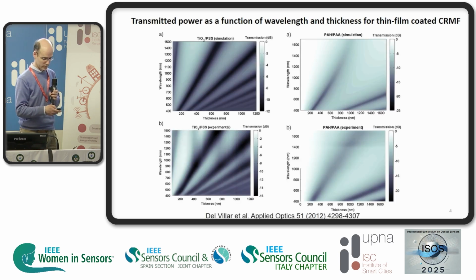This video can be summarized in these graphs. Here we plot the transmission as a function of thickness and wavelength, so each line in this direction is a transmission spectrum. What we can observe here is that this is the first LMR, this is the second, third, fourth. The first one is much steeper than the second one and the third. In addition, this is done with titanium dioxide with a refractive index around 1.9.